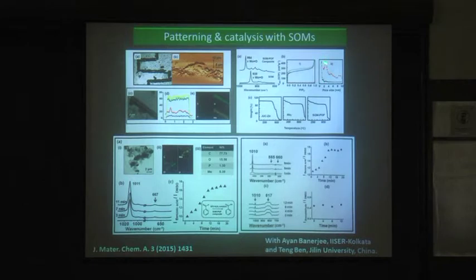In the micropore regime, we see the micropores are blocked here, and you have only the mesopores that are still available, and that means we still have the mesopores available for the reaction, and we believe that the reaction takes place in this mesoporic regime. And if you see the thermogravimetric profile, the SOM-POF composite is much more stable than each of the individual components.